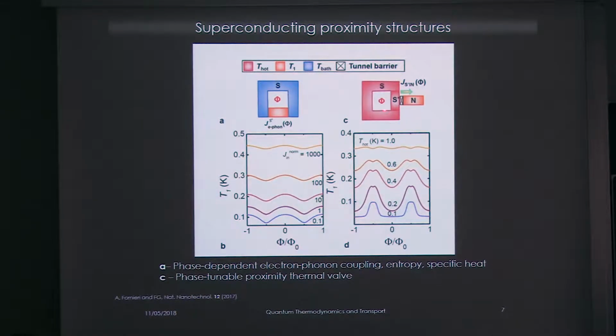What is nice in this kind of system is that in this sort of proximity valve, we can get a cutoff, a complete closing of the heat flow in the system. It's very equivalent to the spin valve in some sense, to an ideal spin valve, okay? It is a sort of ideal thermal valve in which heat can flow or can be blocked. Because, for instance, in the other cases, like for Josephson interferometers, we can just modulate the heat current in the system, but not completely close the heat flow. So this is the second approach.